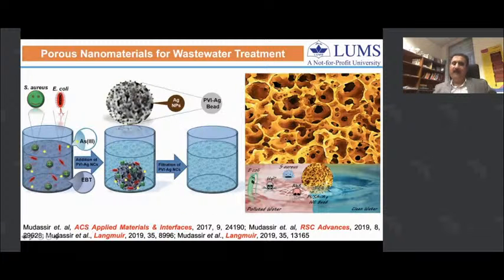More recently, we have extended this approach to develop a variety of new emulsion templated polymers in which you can control the chemistry of the polymer matrix, and then incorporate a variety of inorganic nanoparticles, especially magnetic nanoparticles, silver nanoparticles, and other metal nanoparticles. Because of their higher surface area and porous nature, we use them to remove organic and inorganic pollutants from wastewater, for example contaminated with organic contaminants or toxic metals. This was really useful, and these applications and publications are basically from these types of materials.